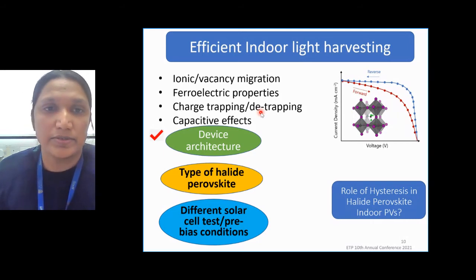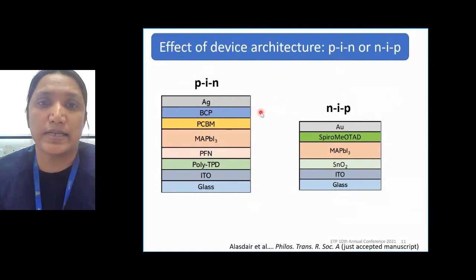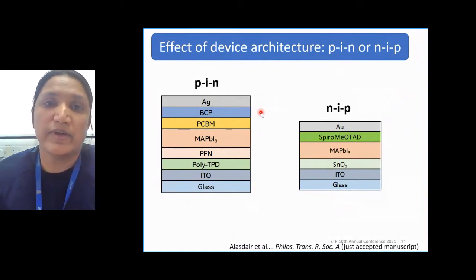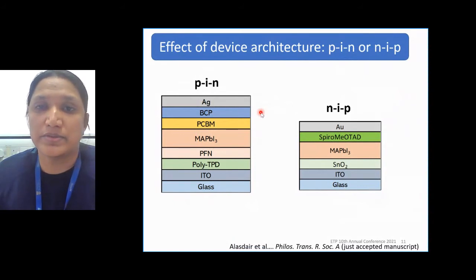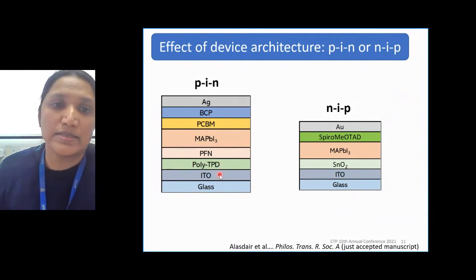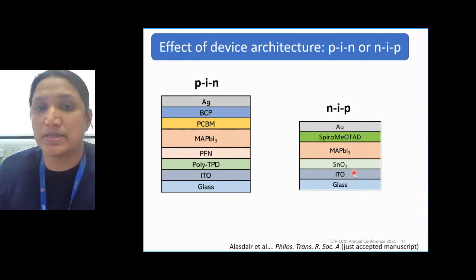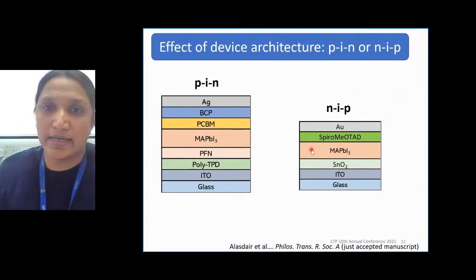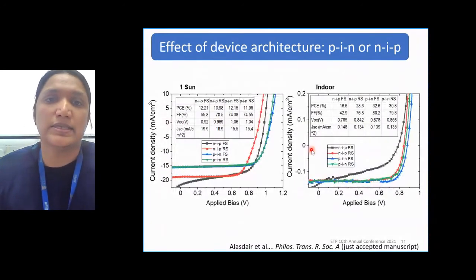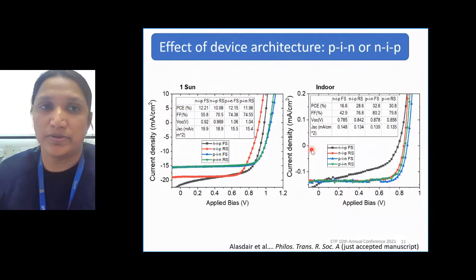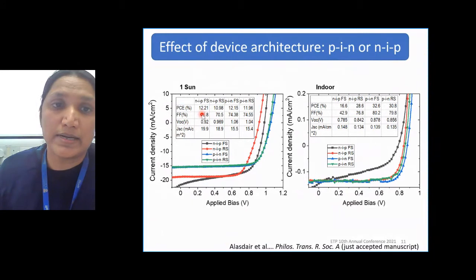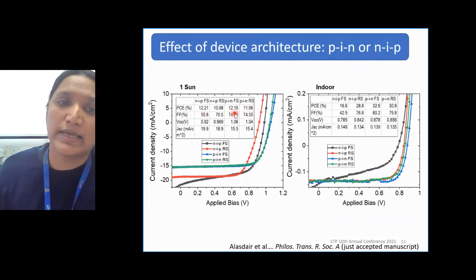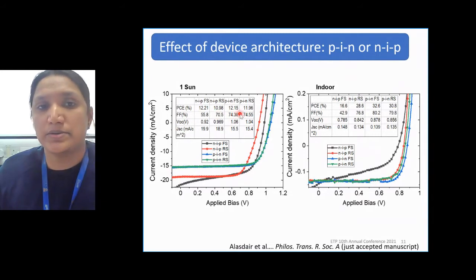Now, coming to the different device architectures we have selected, the two well-known or dominant device architectures used in halide perovskite photovoltaics are PIN and NIP. In the PIN structure, the ITO electrode collects holes, and in NIP, the ITO electrode collects electrons. In both device architectures, we selected methylammonium lead iodide as the active layer. Here it shows the JV curves of the devices under one sun and indoor illumination. Here we can see that under one sun illumination, the power conversion efficiency of both NIP and PIN architectures is quite similar, close to 12%.